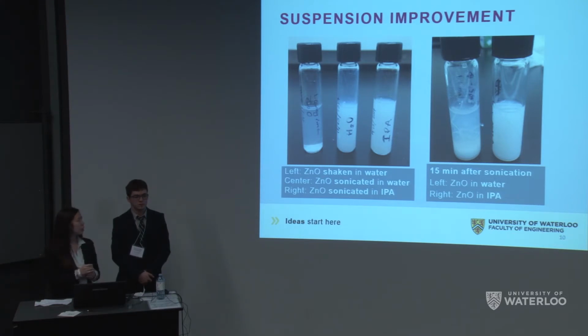So in the image on the left, you can see there's 3 vials. So the first vial is ZnO shaken in water, and by shaken I mean we manually agitated with our hands, because this would actually be the cheapest way to suspend it, but it didn't work very well as all of the nanowires are just sitting on the bottom. And then the other 2 vials are ZnO sonicated in water and ZnO sonicated in IPA.